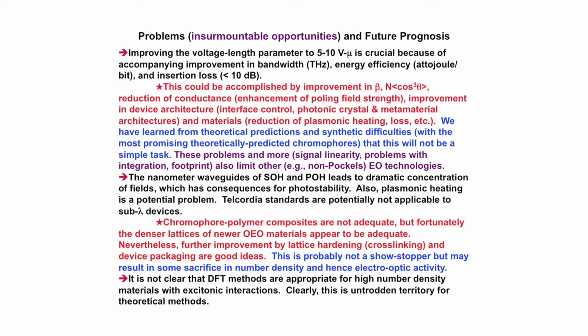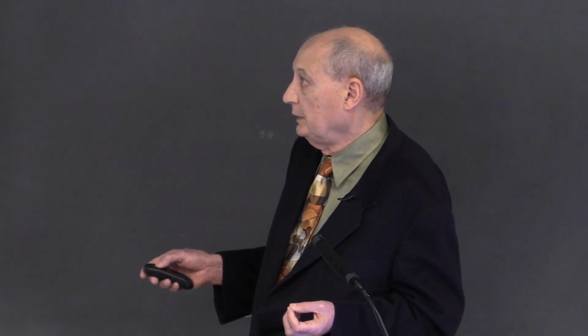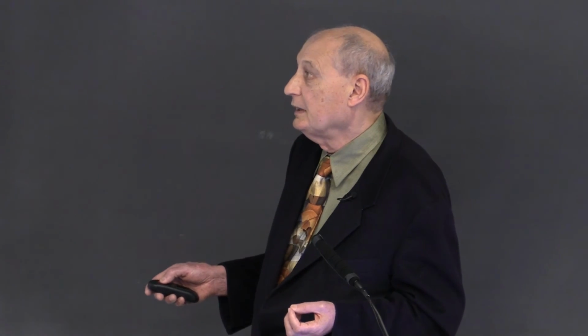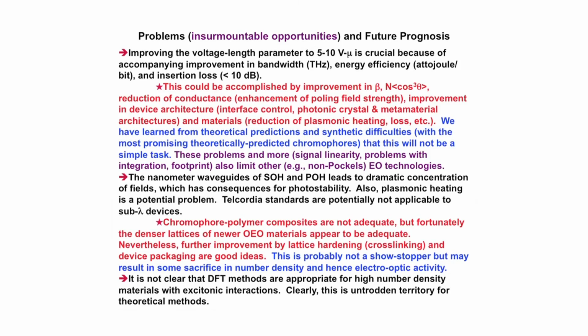Now this could be accomplished in any of these ways: by improving the beta of the chromophore, the product of number density and order parameter, reduction of conductance that occurs at poling conditions, improvement of device architectures, interface control, use of novel photonic crystal and metamaterials architectures, and also by dealing with our inorganic materials, for example, finding new plasmonic materials, using nanostructured plasmonic materials, reducing plasmonic heating and optical loss. Now, we know from our theoretical work and synthetic work, this is not a trivial task to accomplish these. Now, we would note that all these problems and more, signal linearity, are associated with the other non-Pockels technologies.